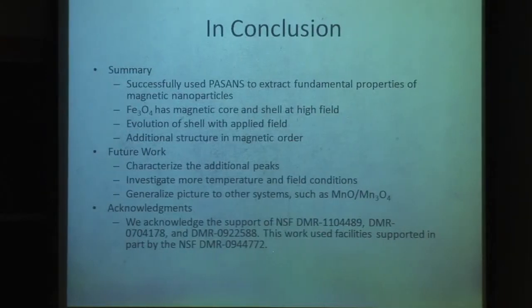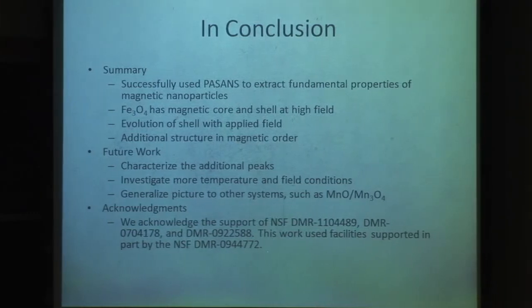So in conclusion, we've successfully used polarization analyzed small angle neutron scattering to extract some fundamental properties of these nanoparticles. And we've seen that our iron oxide particles have a magnetic core and shell at high field. We've also seen some of the evolution of how this shell happens as we change the field conditions. And we've seen some additional structure, or some additional ordering within the magnetic structure that is not present in the actual physical structure. In the future, we'd like to work to characterize these additional peaks and investigate more temperature and field conditions. We'd also like to generalize this picture to other systems, such as a manganese oxide system.